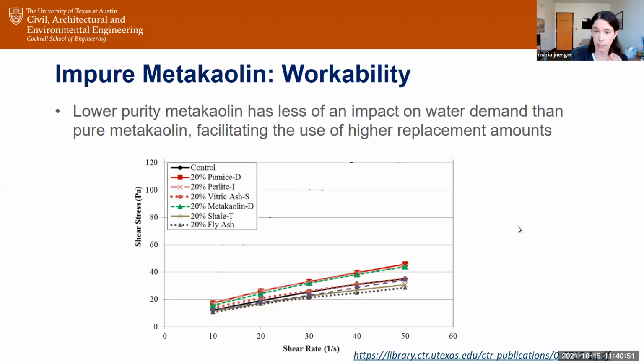So it makes it really stiff and hard to mix and sticky. So people use it in really small amounts, let's say 10%. What we found is that when you use a less pure calcined clay, you can get workability similar to other pozzolans.